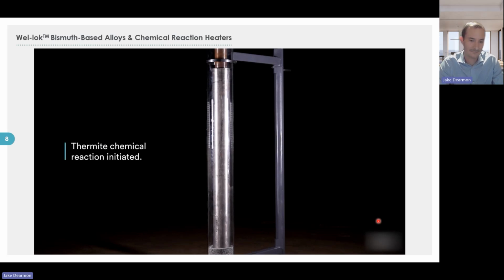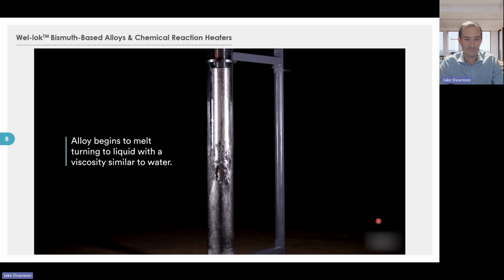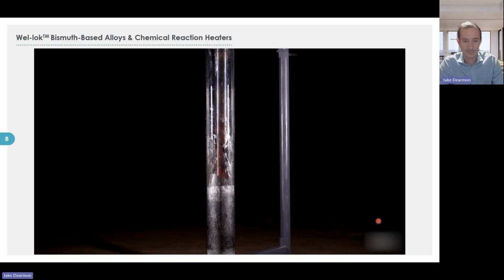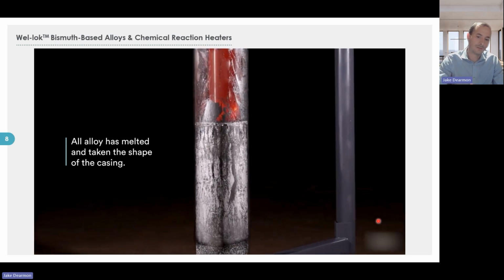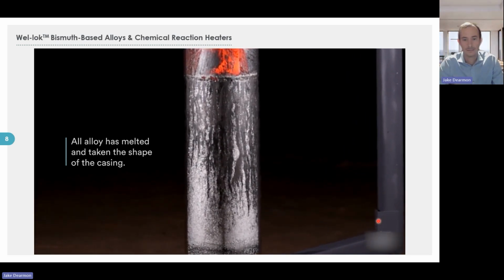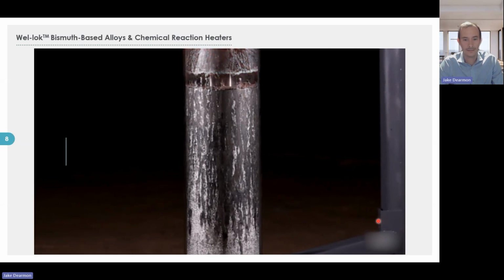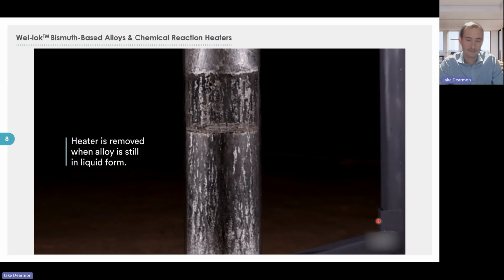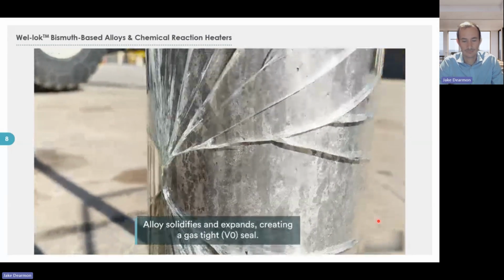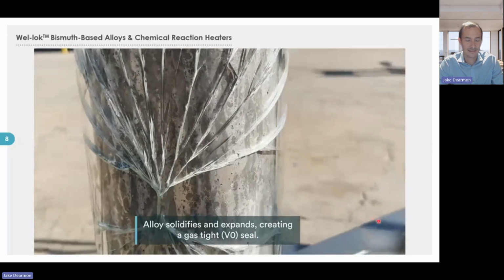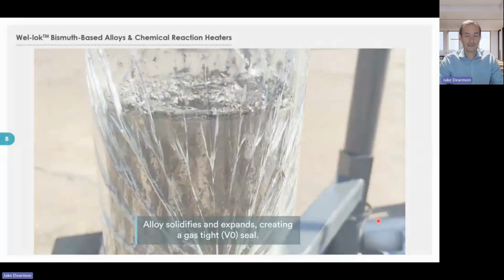So in this video, we have the same controlled thermite and heater with some alloy cast in it. You can see as that thermite burns from the top down, it's melting the alloy. That molten alloy falls off the heater. Eventually, it all melts to the bottom, where in this particular case, like we do in a lot of our plug and abandonment operations, we actually remove the heater, that thermite heater, from the center of that alloy plug. That's to keep one material or one barrier material, rock to rock or casing to casing, and we don't have that heater left on the inside. Flash forward, you see that same expansion property in this Pyrex tube. That's the alloy solidifying and actually creating that hoop stress into the system that gives us that differential seal that we're looking for.